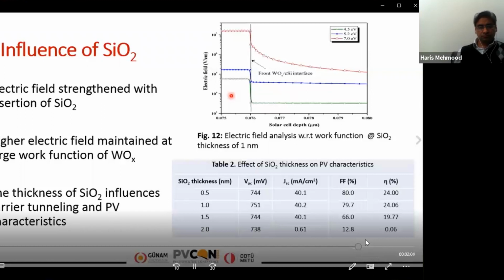And the thickness of the silicon dioxide also influences the carrier tunneling and the photovoltaic characteristics of the proposed device. And we have seen that the optimized thickness of 1 nanometer of a passivating silicon dioxide would warrant the conversion efficiency of around 24%.